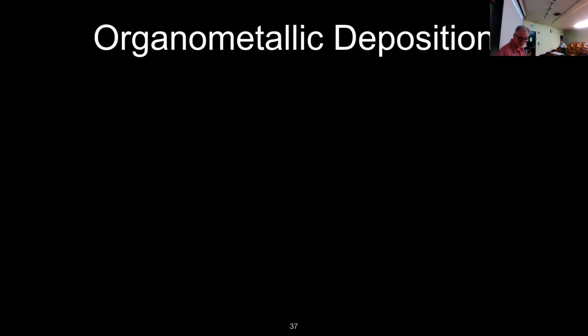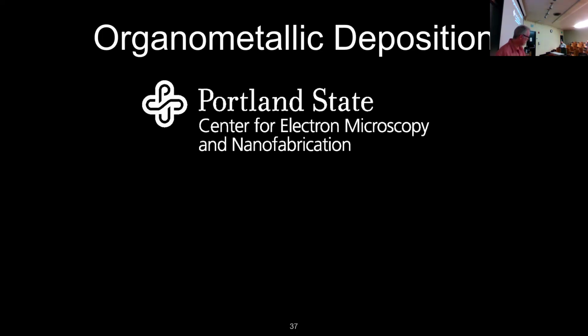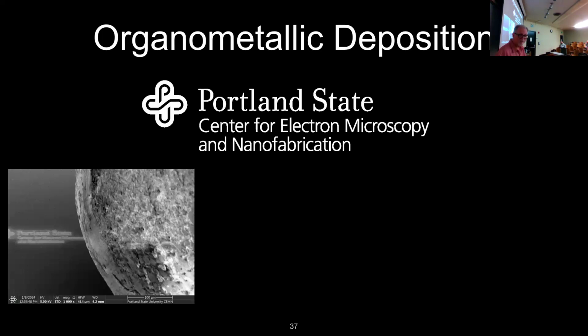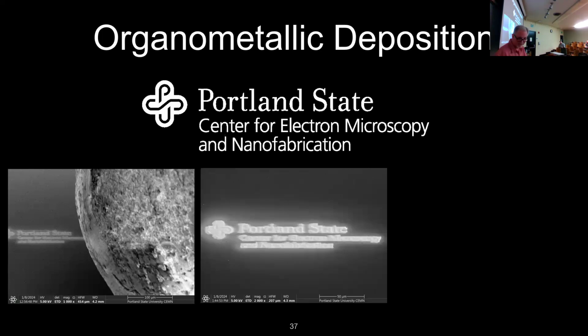And then I did a quick organometallic deposition, which kind of turned into a nightmare, using the inverse of our logo, which is white. And here in the electron beam view, you can see the gas injection needle and a teeny tiny little PSU logo out there. I didn't like the way it was developing because the C and center had some defects in it, so I changed my scanning technique. I didn't move, I just redeposited on top of that. So now it got a little ugly, but I thought, well, I have an ion milling machine here. We can make this better.